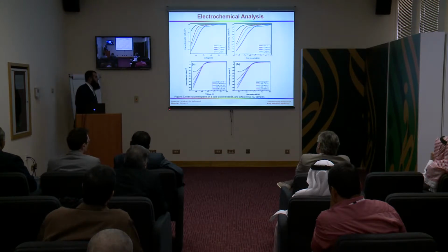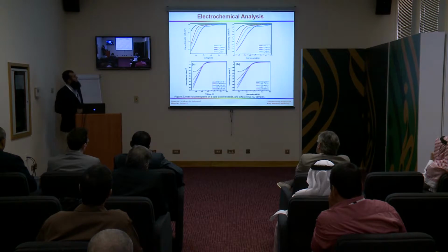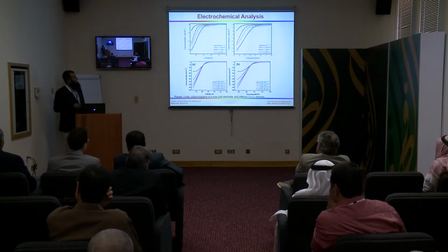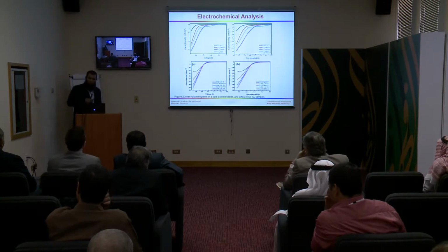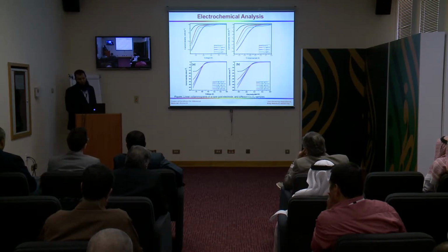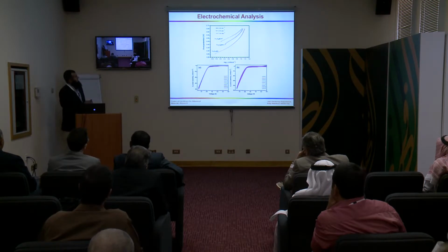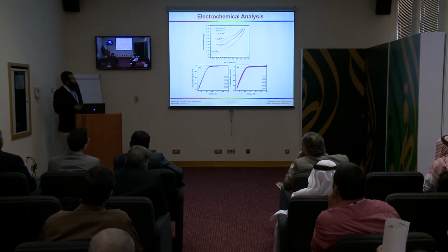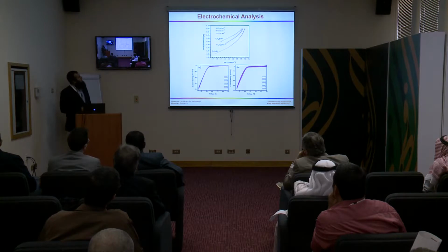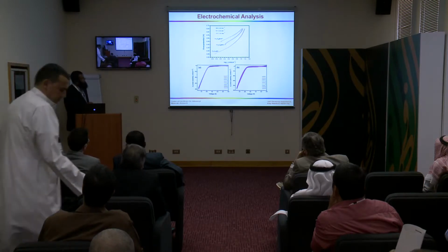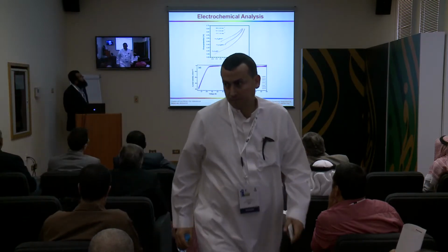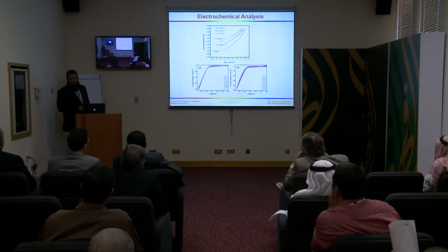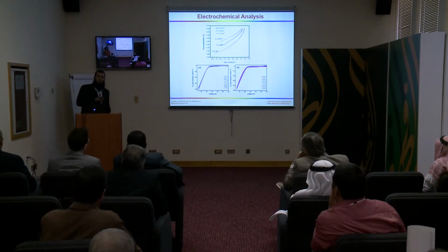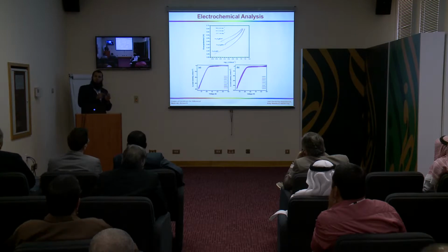Then in a similar way, we studied the effect of different pH, the effect of OH ion, and it clearly shows that the OH ion is important and shows high current density when we increase the pH of the electrolyte. This we calculated from the Tafel slope, and the Tafel slope gives the activity of the material.